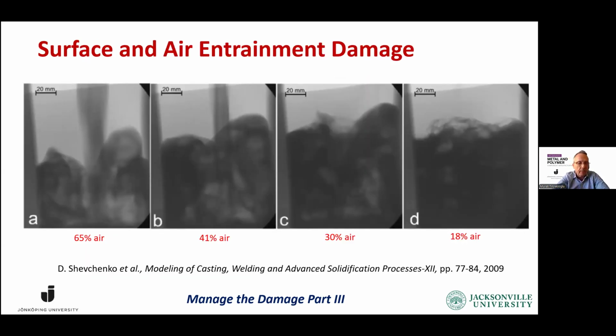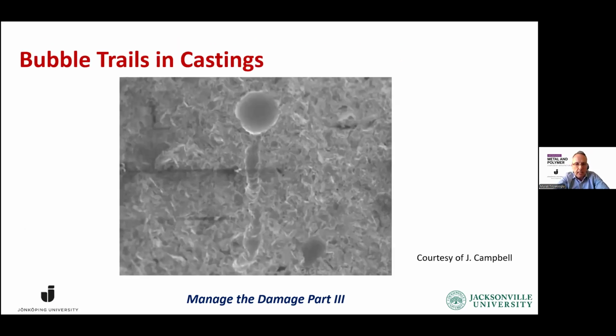And I'm going to show you a picture of that. But when we have this melt transfer, you can see that in the beginning, there's 65% air where the liquid is supposed to be, and that gradually decreases, but we are giving serious damage to the liquid aluminum in these melt transfers. And the bubbles and the air that's entrained has buoyancy. It needs to go up. And you can see here a bubble that tries to go to the surface, leaving behind an oxide trail. That's going to act as a crack when it's under stress or tension. And you can see the bubble here that has had to stop because of the impinging solidification in front of it. It could never go to the surface.